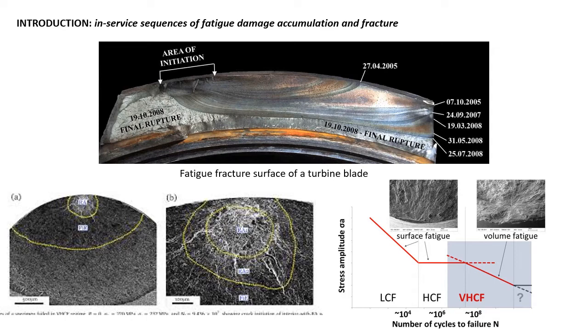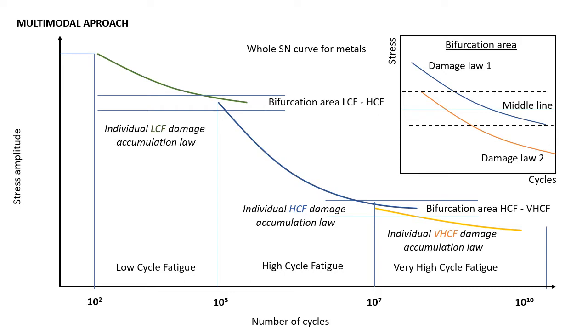This work introduces a multimodal approach and numerical algorithm for calculating the progressive fatigue damage accumulation and failure with respect to the loading mode based on the stress amplitude. In order to describe a full SN curve, the multimodal approach is used. The main idea is to distinguish three different regimes with its own mechanism and description of the fatigue damage accumulation by individual laws. The change in mechanism is not sharp, that is in good agreement with the physically based researches of fracture processes.